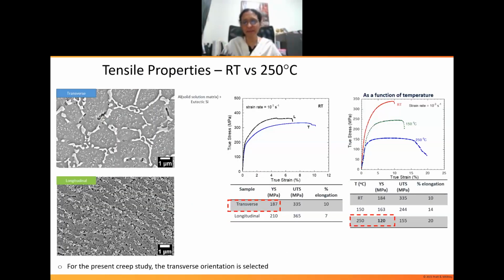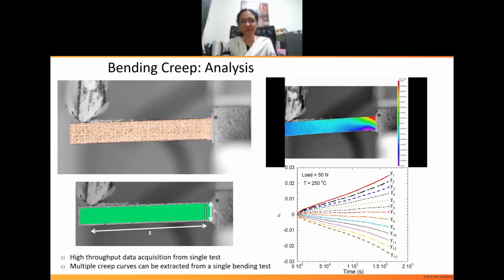This particular example that I'm sharing with you is how we are able to delineate between transverse versus longitudinal build orientation. Remember, I told you that is a big challenge in additive manufacturing because of residual stresses, because of the nature in which it is printing layer by layer. This is a particular paper that we shared at ICAM 3D, showing how high throughput bending can distinguish between microstructural differences in a very quick manner using one bending creep specimen. And of course, that's what I'm sharing with you here, the creep analysis.